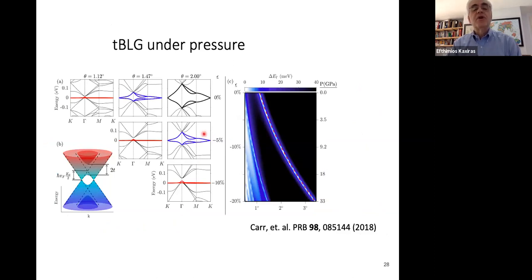For example, consider what happens if we put the system under pressure. So what you see here is a certain twist angle, 1.12 degrees, and the flat bands that I just mentioned highlighted in red. Then a different angle here, 1.47 degrees, and the bands here are not that flat. But if you compress these layers by 5%, you get again very flat bands. Alternatively, you can put a different twist angle, 2 degrees. Again, the bands are not flat at all at zero compression, but they become very, very flat at 10% compression.